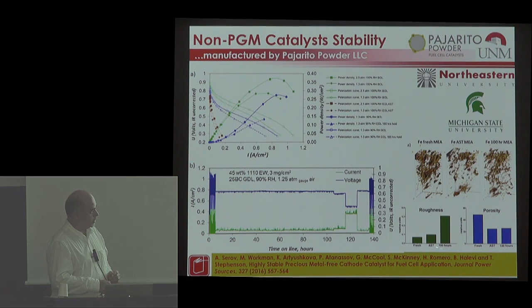Because if you form water in micropores, in pores that are smaller than 10 nanometers, there is no way you will take that water out. And if a substantial amount of catalyst active sites are in those pores, your oxygen will never reach them without diffusion through water, at least. So remember the agglomerated flooded core-shell model that Frederick was showing. That stops working, and the catalyst moves into a fully flooded model, and the performance goes down, manyfold.